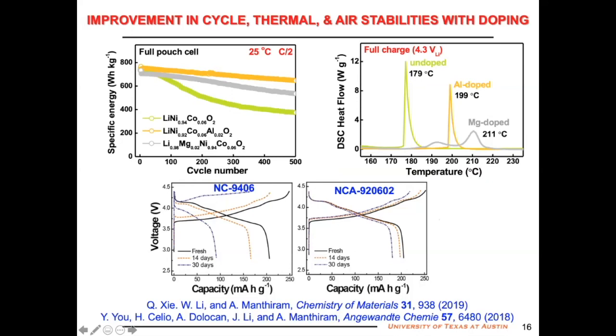I'm comparing here the cyclability again, undoped versus aluminum and magnesium. Again, you can see doped samples have better cyclability. Doped samples also have better thermal stability compared to the undoped. I'm also comparing the performance after exposing the undoped and doped material to air. As you see here, the undoped material after exposing to air for 14 days or 30 days degrades much compared to the material with 2% aluminum, which shows less degradation.